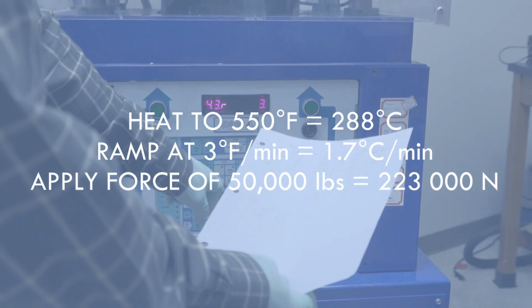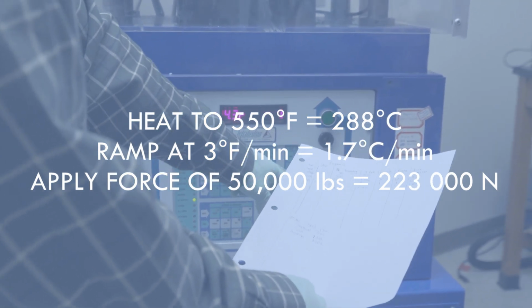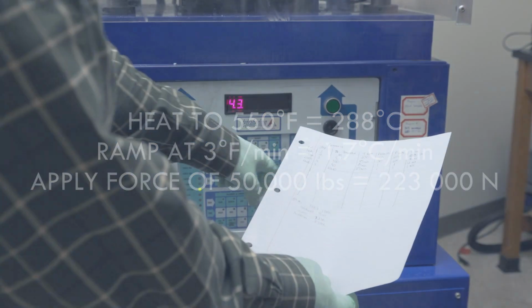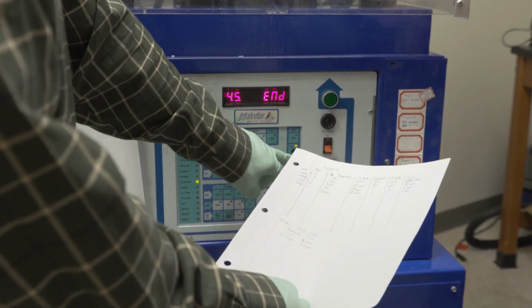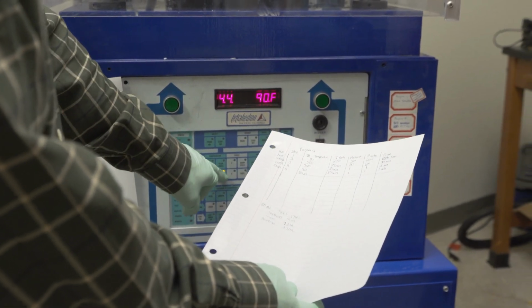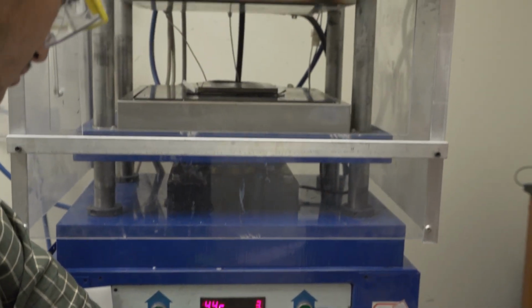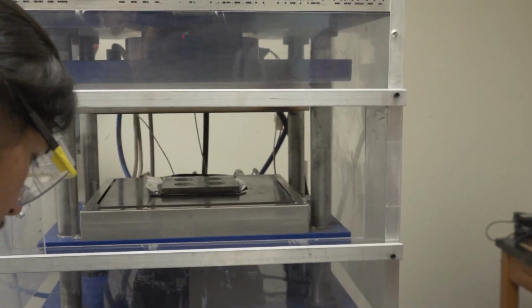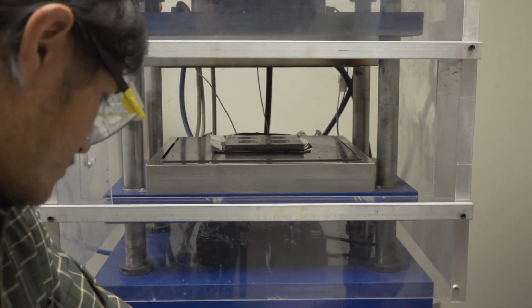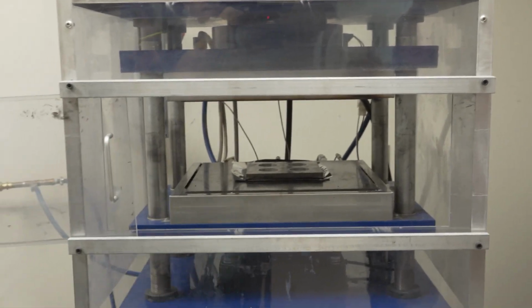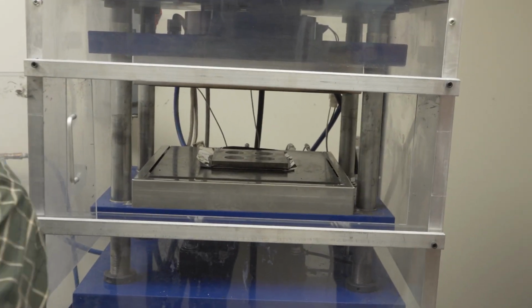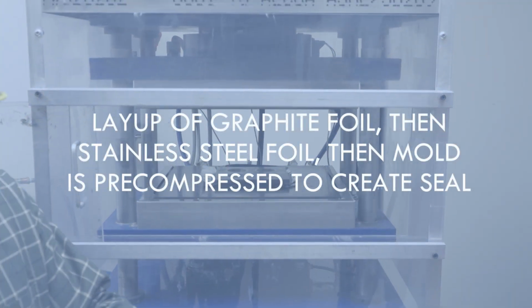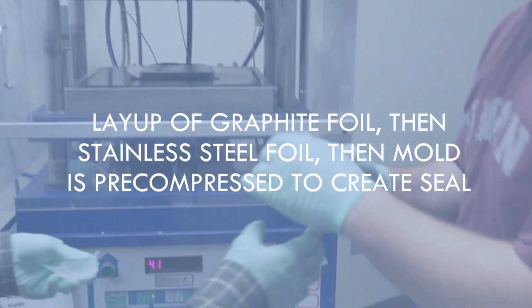We heat it to 550 Fahrenheit, hot presses in English units, and they're applying a force, in this case, of 50,000 pounds. So what's inside the press? That's the mold. So what we do with the mold, it's an open bottom mold, and they lay it on the gasket material, which consists of graphite and then stainless steel. And we pre-compress that to get some sealing so that we don't end up with the material leaking out.